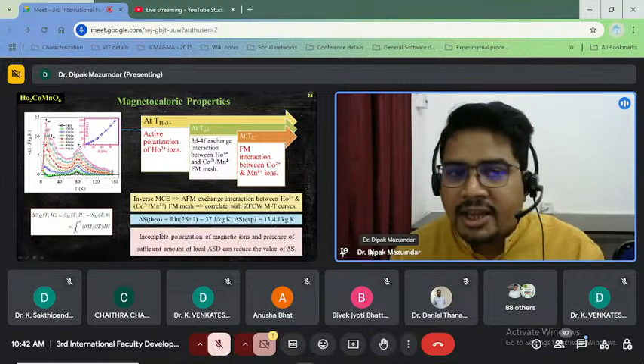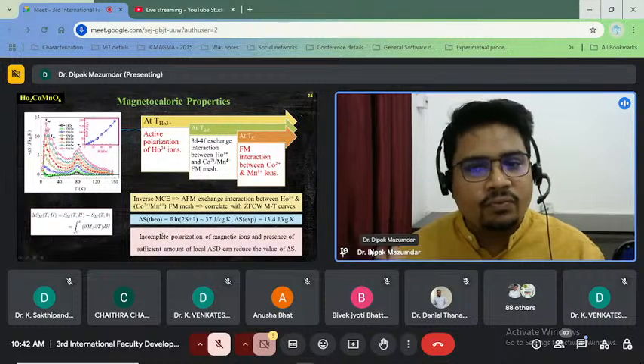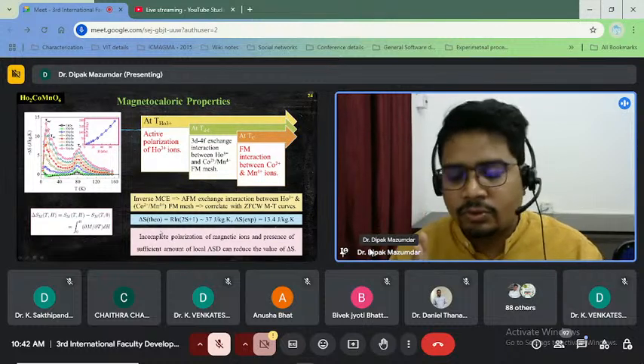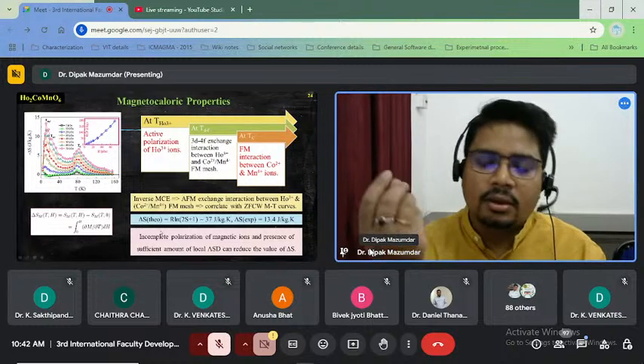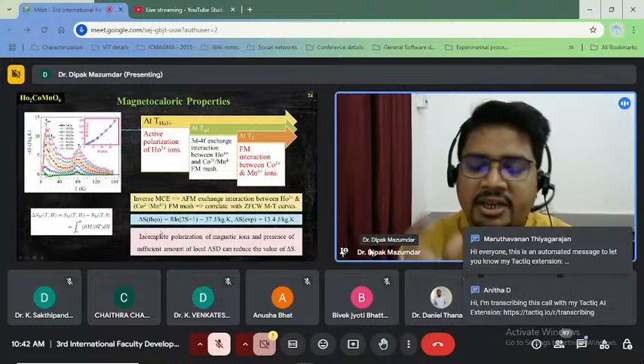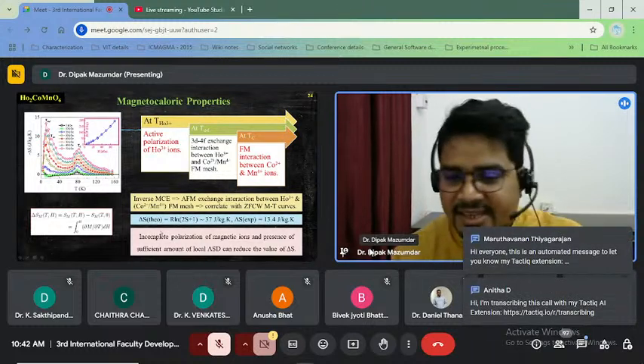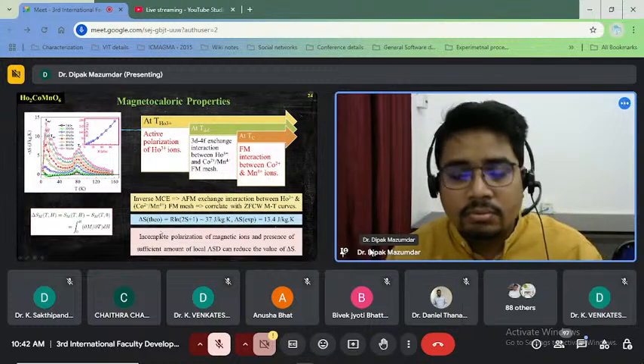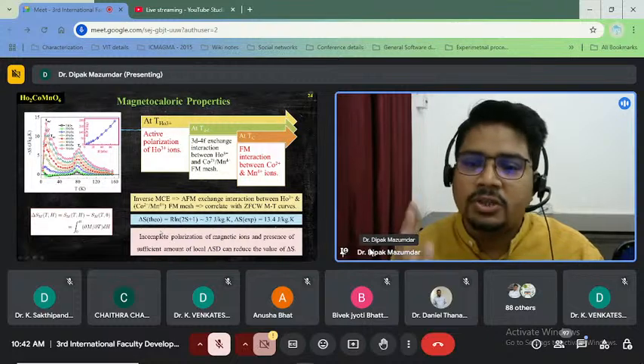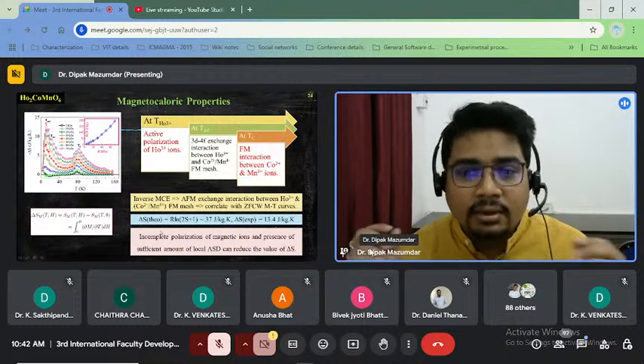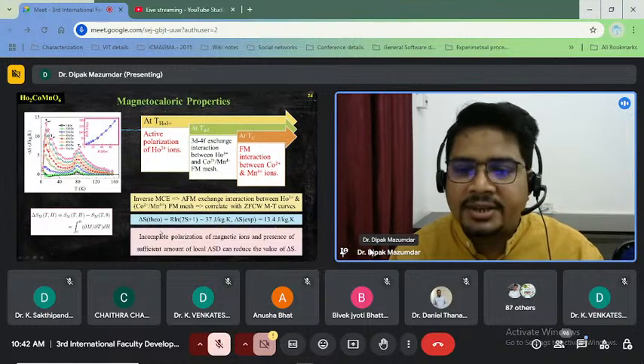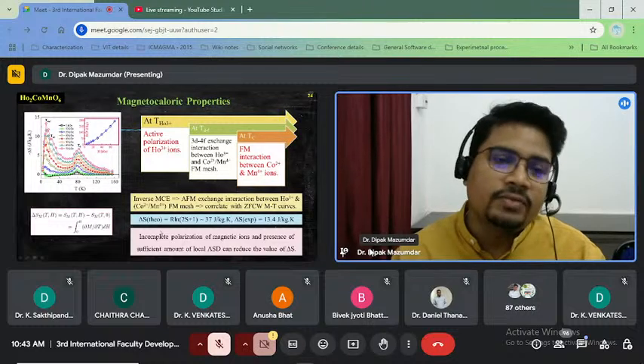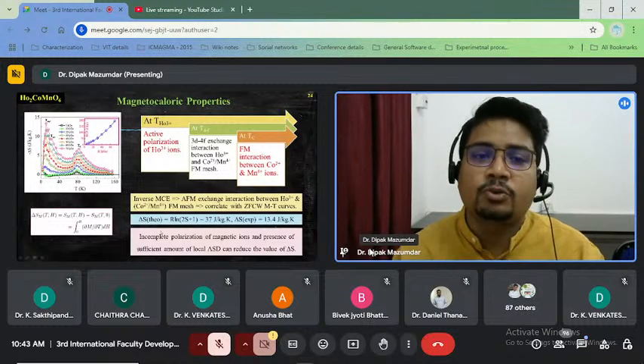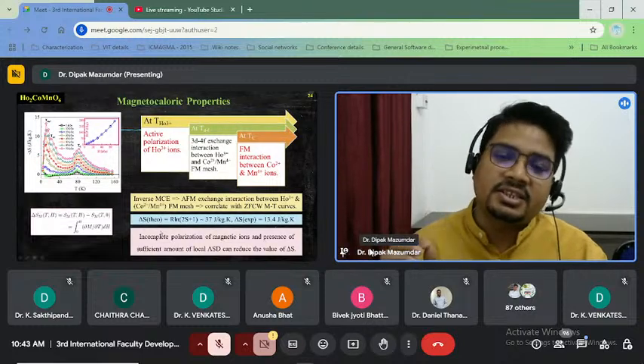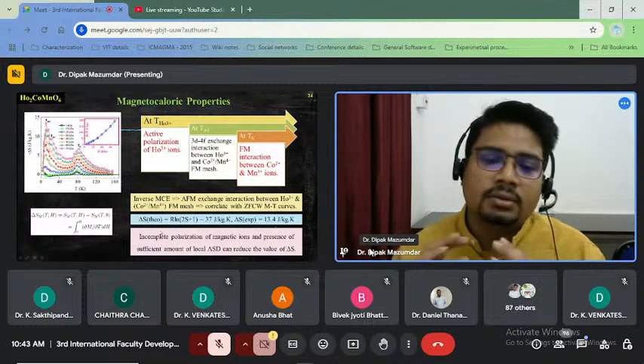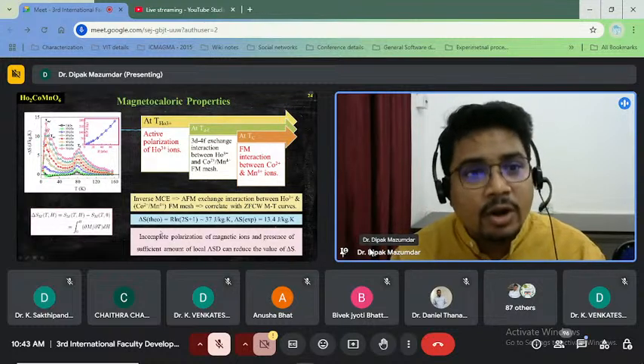One is incomplete polarization of magnetic ions. That means the holmium ions are not fully saturated. If they were fully oriented, then we would achieve a saturation magnetization of around 26 μB per formula unit, which I discussed in my last slide. So maybe there is an incomplete activation of these holmium ions in this low temperature region, and maybe a sufficient amount of local anti-site defects is present in the system, which can reduce the value of delta S. We did not have any probe at this moment to check how much anti-site defect is present in the system. So we can just assume that there should be anti-site defects or incomplete polarization in the compound.